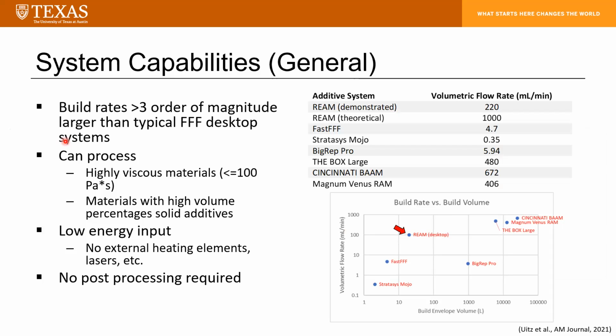So a couple of notes about REAM systems generally and their capabilities. As I mentioned once or twice by now, we can achieve very large build rates in excess of 3 orders of magnitude greater than your standard FFF system. So here we have down at the bottom of this graph a Stratasys Mojo, which is a fairly typical entry-level desktop FFF system. And over here we have our desktop REAM system using the volumetric flow rate that you just saw in the previous video, just over 100 milliliters per minute. Though it is notable that we've demonstrated volumetric flow rates of 220 milliliters per minute.